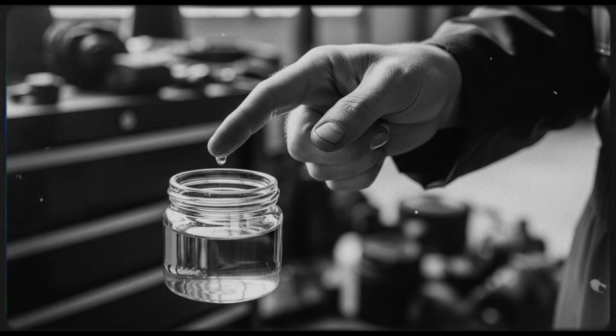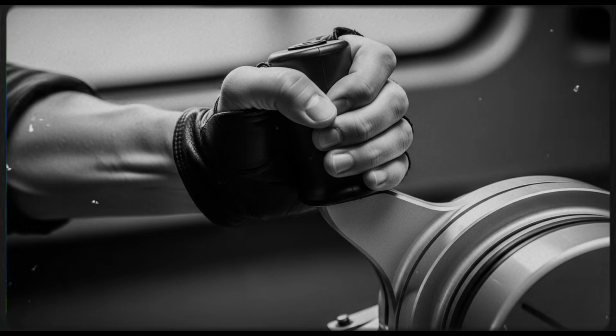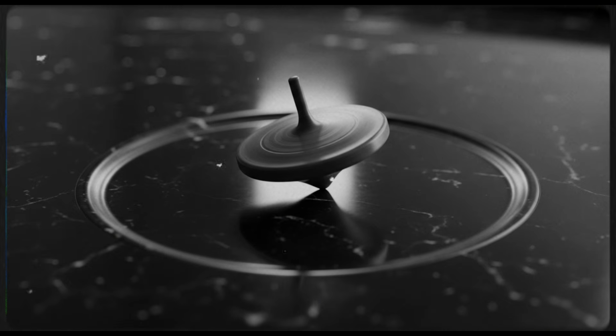Fletcher persuaded his superiors to order a batch of steel blanks. They showed up in November 1940. The new steel rings were meticulously cut, formed, heat-treated, and finally sent to the plating tanks. Once they were ready, Fletcher carefully installed them in a test engine. He started it up. It ran. 1 hour, 2 hours, 5, then 10 hours passed with the engine screaming at maximum throttle. 20 hours, 30 hours, 40.